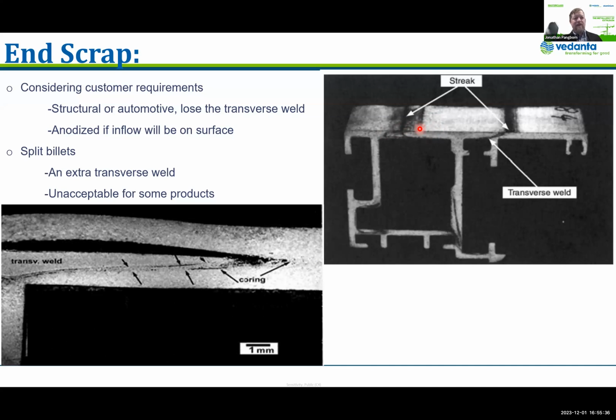We went from 1 inch to 1.5 inch butt to push a little bit less into the die, and then we increased the scrap requirement at the back. I'm not positive on the numbers, but something like from 3 to 5 feet, and we avoided what in the black anodized showed up as these white lines. We avoided that completely and fixed the issue that was plaguing us at the time.